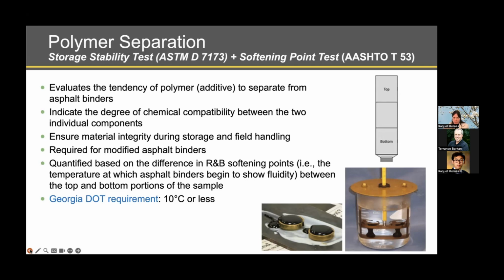The softening point, what is it? It is an indication of the fluidity of the binder, meaning what is the temperature where the binder will start to flow. Why is this property important? Well, imagine that we have a pavement that is to be located in a location that has an environment temperature of 40 Celsius. So we want to have a binder that has a softening point that is higher than 40 Celsius, meaning that that material is not going to be soft at that specific environmental temperature.